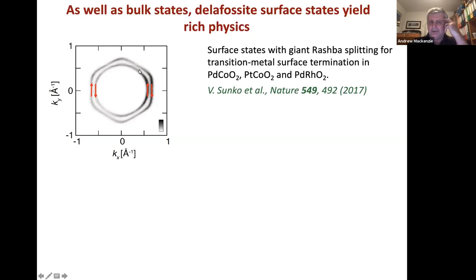So those are the two Fermi surfaces of surface states. And Phil King and Veronica Sunko and collaborators did some spin resolved photoemission to confirm that the spin orientation is opposite on the inner and outer state. Right? And the thing that Veronica worked out, which is amazing here, is that everybody knows, in inverted commas, that giant Rashba splittings happen in very heavy materials with huge atomic spin orbit coupling scales, right? But actually what limits the Rashba split that you observe is the lesser of the inversion breaking scale and the Rashba scale.